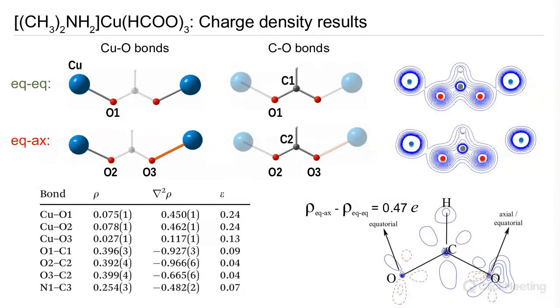We can also subtract the charge density evaluated for the equatorial-axial formate from the equatorial formate, and we find a difference of just half an electron across this whole formate structure. So, with a view to applying the Goodenough-Kanamori-Anderson rules, we can move forward under the assumption that these two formates, electronically at least, appear to be the same, and that's a result that we wouldn't have got without this charge density analysis.